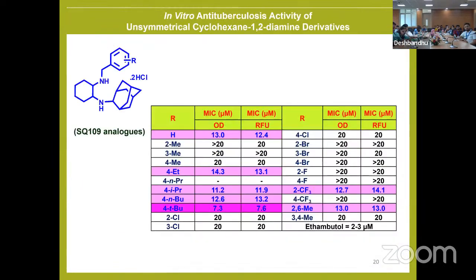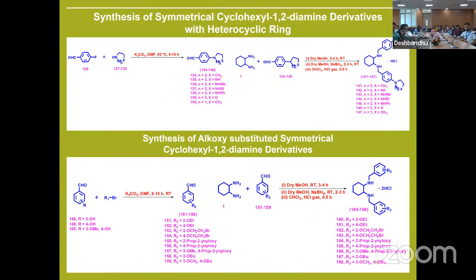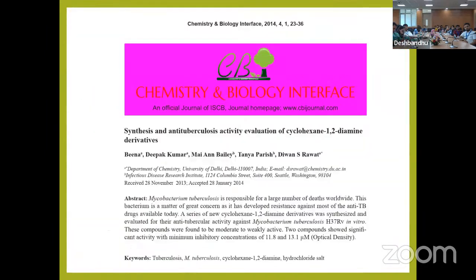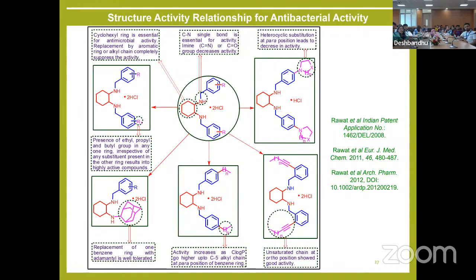anti-TB activity. Then we synthesized a lot of compounds so that we can have a very good structure activity relationship. From the structure activity relationship, we could infer that this adamantyl ring is well tolerated during activity. This cyclohexane backbone is essential for activity, and alkyl chains at the para position of the benzene ring show good activity.